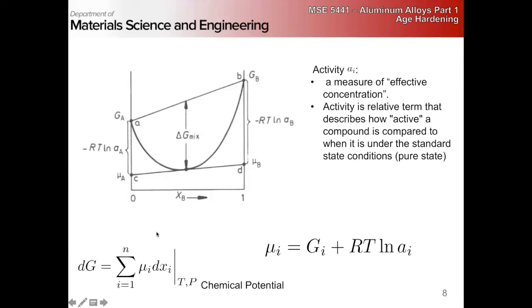So if we take a look at the plot of free energy as a function of composition, here we have a negative delta G of mixing, so it's going to be negative all the way through. So here's what if I just did a tie line between the free energy of pure A and the free energy of pure B, we're always below that, right? And if we look at a particular composition, the delta G of mixing is given by the distance from the tie line down to the free energy curve, right?